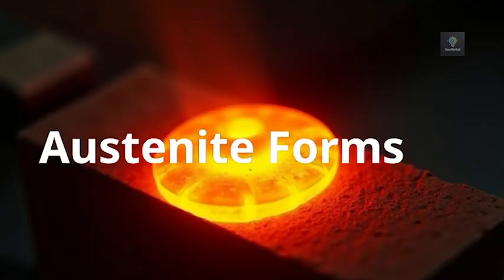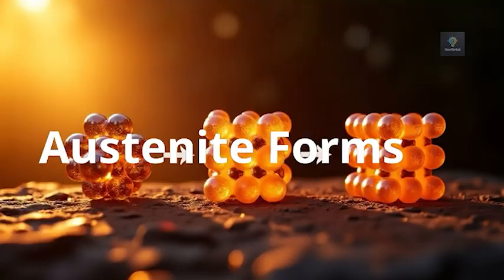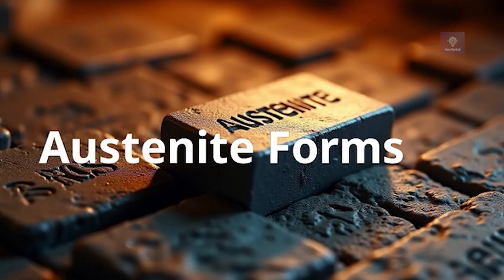Above 912 degrees Celsius, iron becomes more stable in a completely different atomic arrangement. It undergoes a phase transformation. The atoms shift from that body-centered cubic structure to a face-centered cubic structure, where atoms pack together more closely and efficiently. This FCC form of iron is called austenite. The ferrite to austenite transformation happens at 912 degrees. As temperature keeps climbing, iron actually changes back to ferrite at 1394 degrees, before finally melting into liquid at 1538 degrees. These different solid phases are called allotropes of iron, and engineers assign Greek letters to each one for convenience.